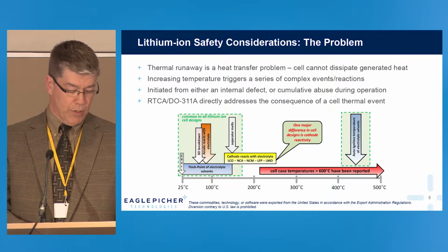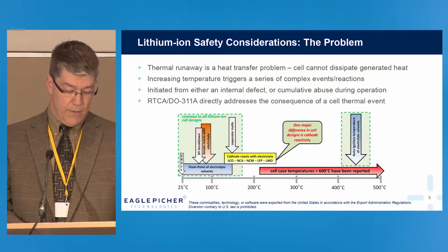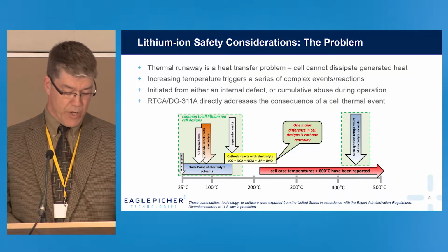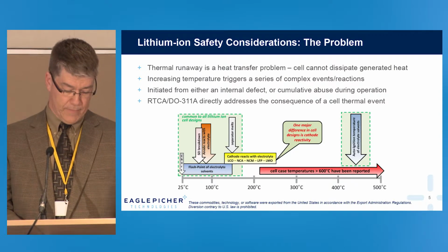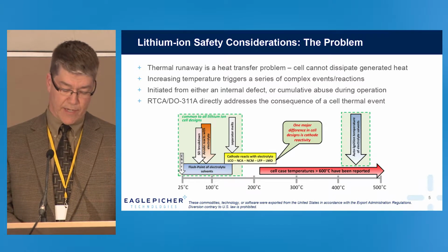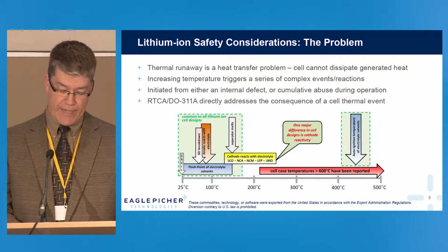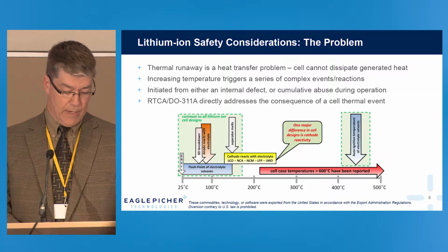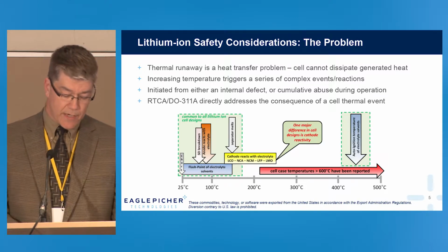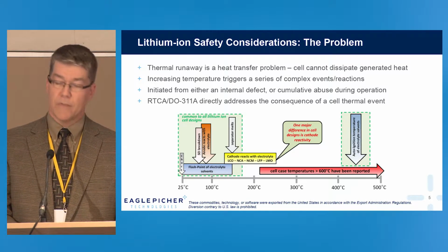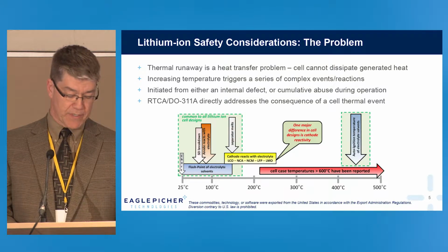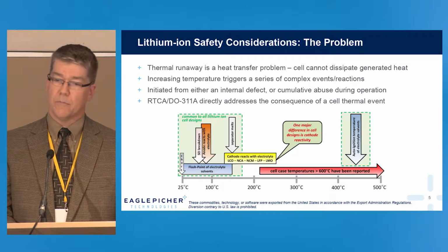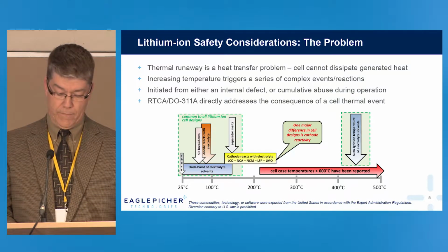So as we look at the problem, thermal runaway involves a degradation of the lithium-ion cell, and it progresses as the cell is unable to shed increasing heat. A hotspot or internal short circuit feeds decomposition of the cell components. Of course, this varies as a function of the specific cell electrochemistry and component selection within the cell, but the progression is similar for all cells.